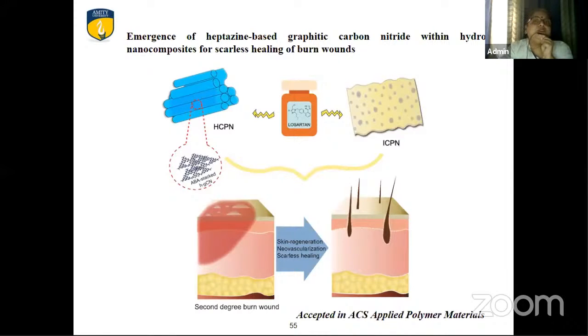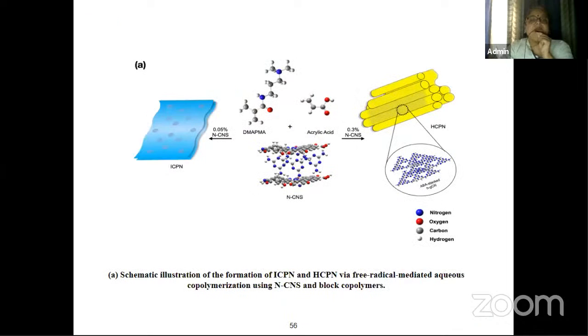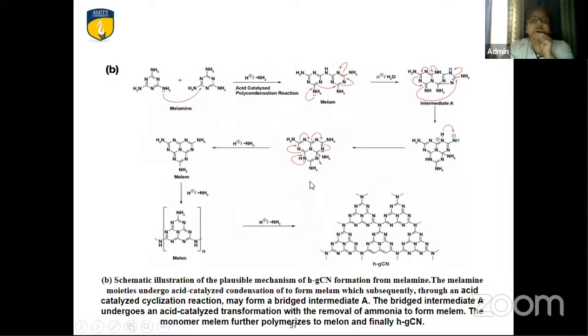Normally graphitic carbon nitrides take very high temperature. So this is the first report, and it has been accepted in ACS Applied Polymer Materials with an impact factor of 12.5. And this is the schematic. As I told you, the melamine is incorporated in between the sheets. And this is the scheme.